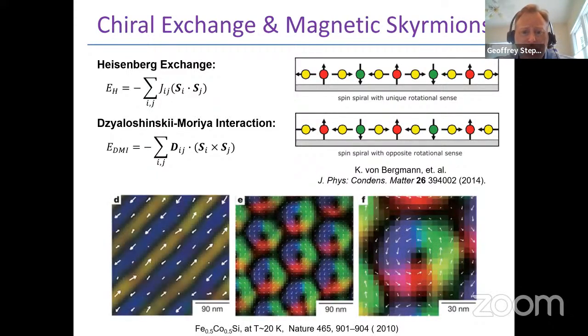When both of these interactions are present, one can have very rich spin textures in materials. Spin spirals can be a ground state, or very interestingly, magnetic skyrmions can be a ground state. And a magnetic skyrmion can be thought of in a simple way as a domain wall that's wrapped around itself to give a circular domain, and that domain can be very small. But one thing that makes this kind of spin texture particularly interesting is that it is topologically protected. That is, there are no defects in the spin winding, so there is no way to continuously deform a magnetic skyrmion from its existence to the ground state or vice versa. So there's a topological barrier in the spin fabric that protects it.